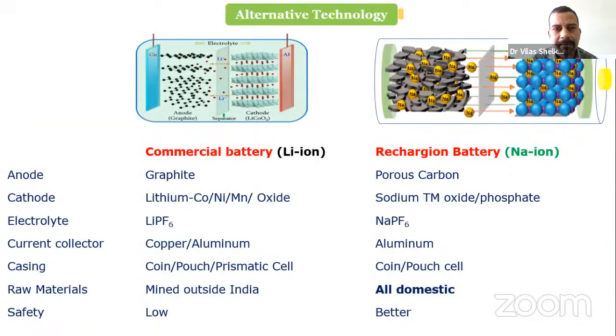So what is the solution then? We need an alternate technology. The commercial lithium-ion battery uses graphite as an anode material. A new technology based on sodium ion has been pioneered by the Faradion company based in the UK. It started with the invention of porous carbon as an anode material, because graphite is not suitable for sodium ion. Sodium is a bigger ion than lithium. So the spacing between the graphite layers is enough to accommodate lithium, but it is not enough to accommodate sodium ion. When porous carbon was discovered as an alternative anode material for the sodium ion battery, only then could this battery operate at a sufficient energy density.